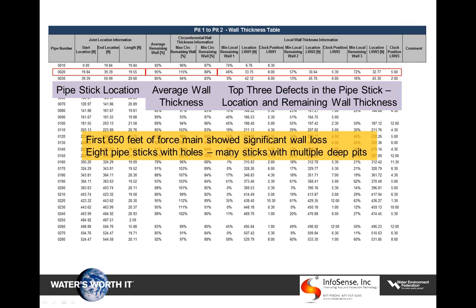What the client was excited about was that this showed that the first 650 feet of the force main had significant wall loss. A lot of sticks with multiple deep pits, and 8 actually had holes in them, probably filled with graphitic plugs. So they weren't leaking, but they still had the holes through already. What's interesting is that most of these defects were in the invert, whereas the pipe earlier had failed in the crown.